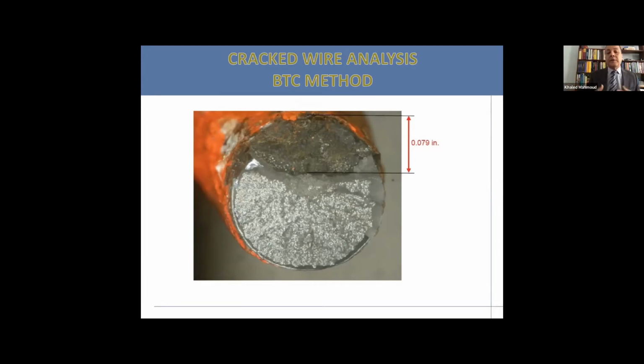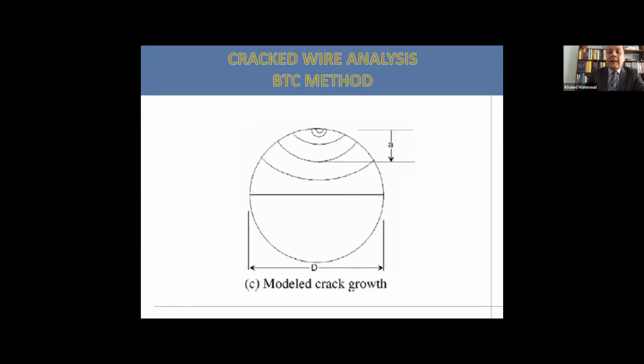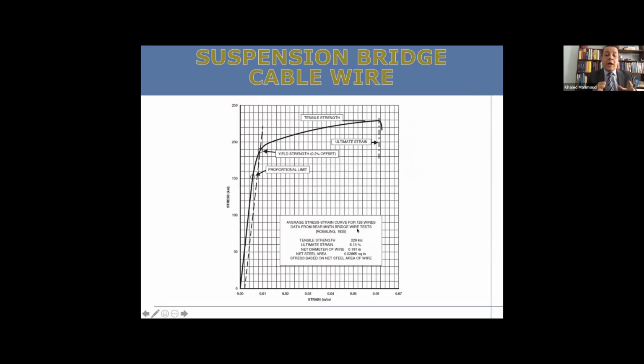This has happened few times. It happened here in our country about 15 years ago with the Waldo Hancock suspension bridge, where the entire bridge was replaced. Actually, it happened in France with the Aquitaine bridge, and Tancarville, where the suspension cables have been replaced. Here's just a schematic of the model of a crack, where you start having the crack starting very early at the edge, and then start propagating up until it reaches critical depth. Now, let's look at how this comes about, and the ramification of that to our knowledge about maintenance, and how to enhance the longevity and improve the performance of suspension cables.